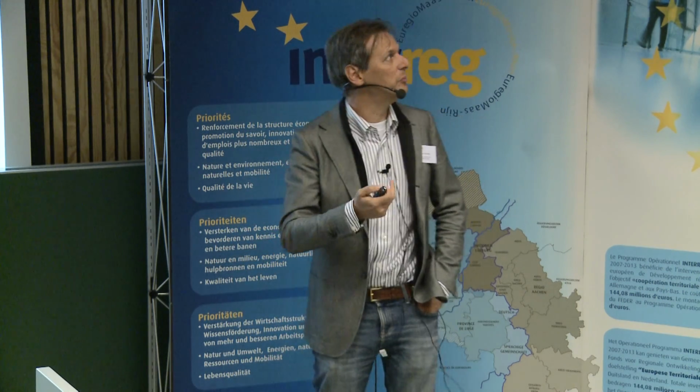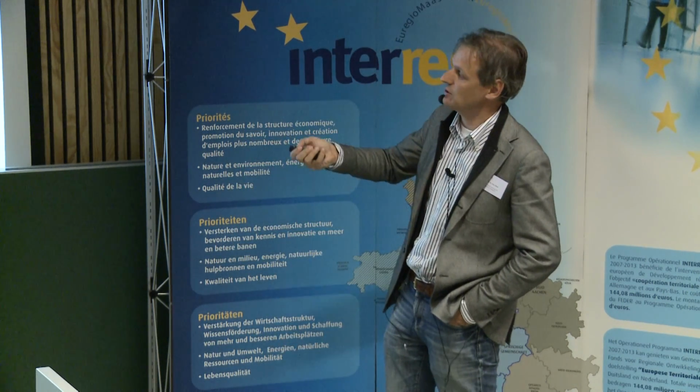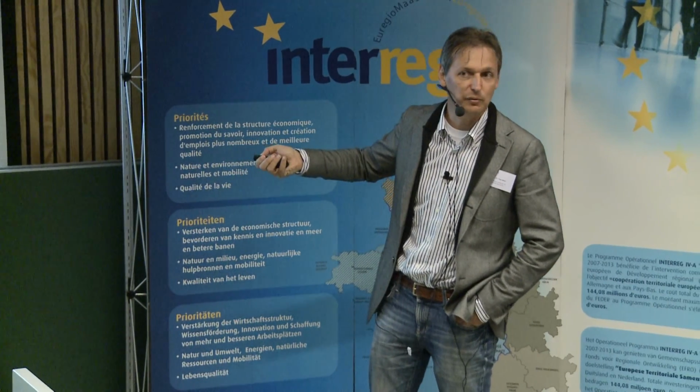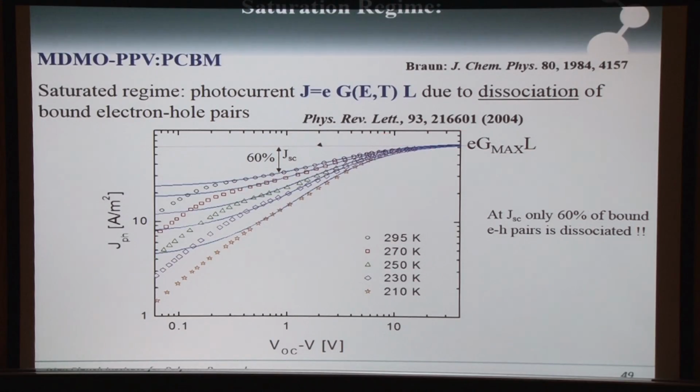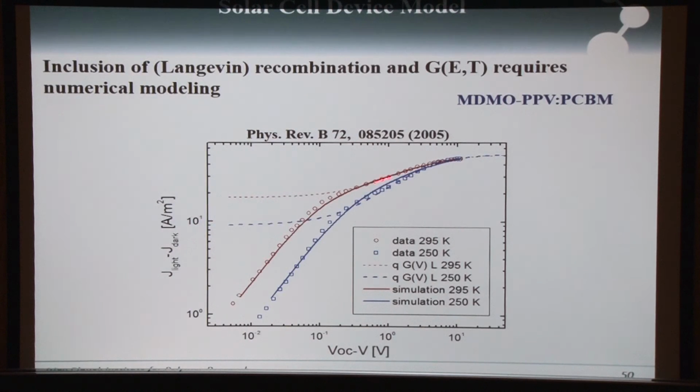But so before the break, what I want to say is if you take an organic solar cell and put it at minus 10 volt, then you can determine exactly how many carriers it has absorbed. You can also look at short circuit current, how many carriers are not dissociated there. And as I said, with a simplified model, you can basically nicely describe the characteristics completely. But you just have to be careful that the two parameters in there are not the real electron-hole separation and the real lifetime of the pair, because there are still a lot of things underneath, like the morphology. Then break.